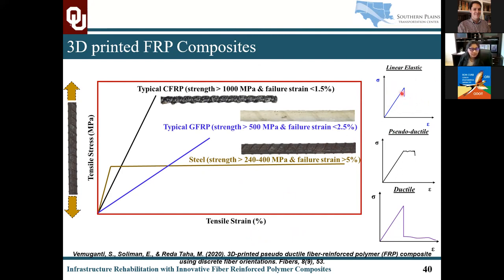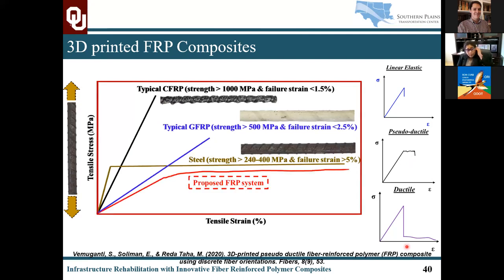So this linear elastic behavior has been attempted to change and transform into pseudo-ductile behaviors, but very low strains were still observed and the strength decrease was very significant. Ductile behaviors were observed, but though they looked at larger strains at failure, that failure strength was very low, which really produced negligible improvements. The proposed FRP system that I have looked at, and also we are looking at currently, is more ductile, having a high yield plateau and high failure strengths, but also preserving that strength and stiffness and coming close to what steel can offer.